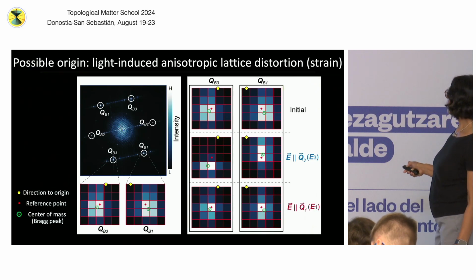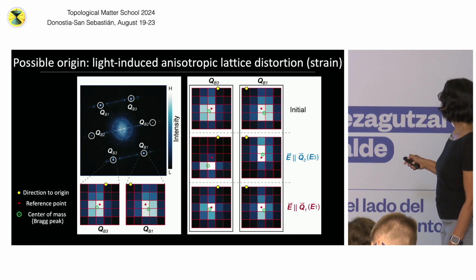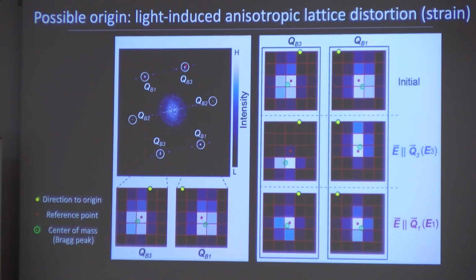So here are the Bragg peaks, the 6 Bragg peaks, right? The CDWs are very faint. You can see them here, 1, 2, 3, 4, 5, 6. So let's just focus on these two Bragg peaks. This is QB3, QB1. Before shining light, this is where the Bragg peaks are. When you shine light along Q3, which is this direction, you can see the Bragg peak moves. So this CDW will get more intense, and the Bragg peak has shifted.